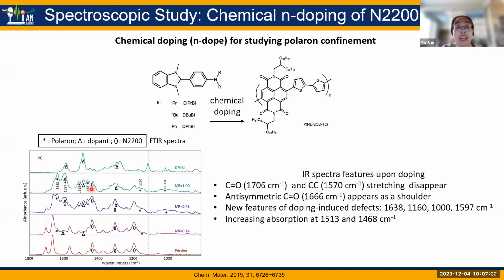So there are several IR feature changes observed upon doping. Firstly, the carbonyl stretching and also CC stretching of pristine N2200 disappear upon doping. And meanwhile, there are new features which are denoted by this asterisk mark, which shows 4 new spectral features appear. And they believe this is related to the polaron formation. And meanwhile, they also see the increasing absorption of these 2 peaks, because these 2 peaks already have bands in the pristine case, but the absorption increases after doping. So in summary, they basically see the vanishing of some of the peaks from neutral N2200, new peaks related to polaron, and also increasing absorption of existing peaks.